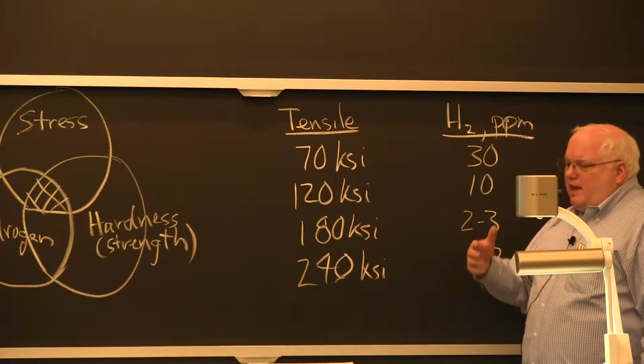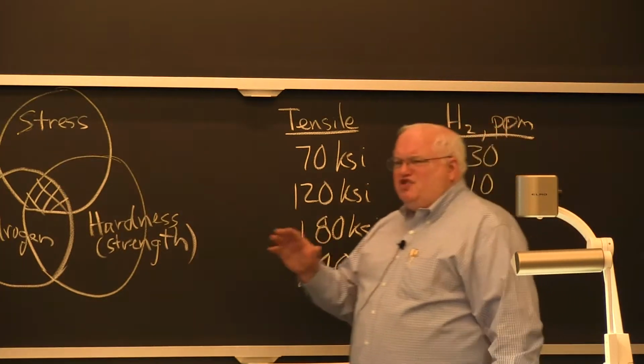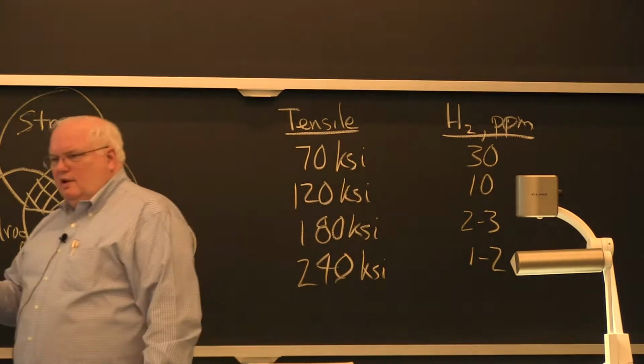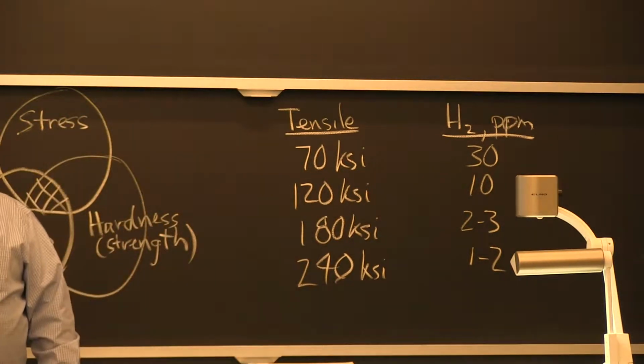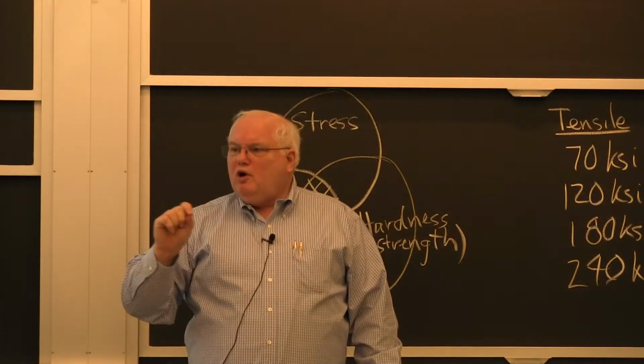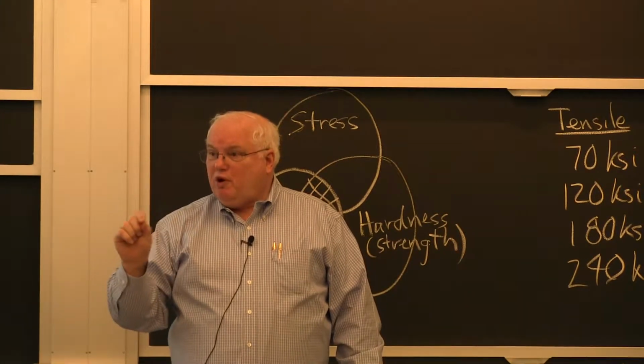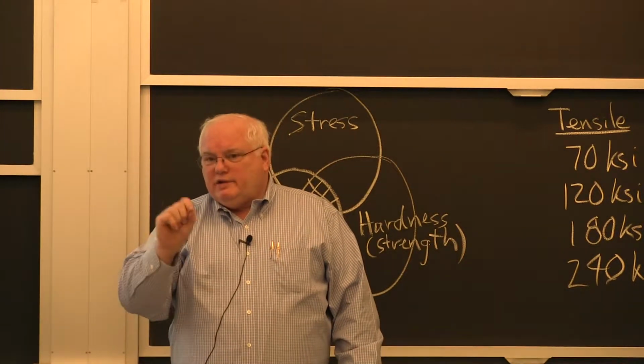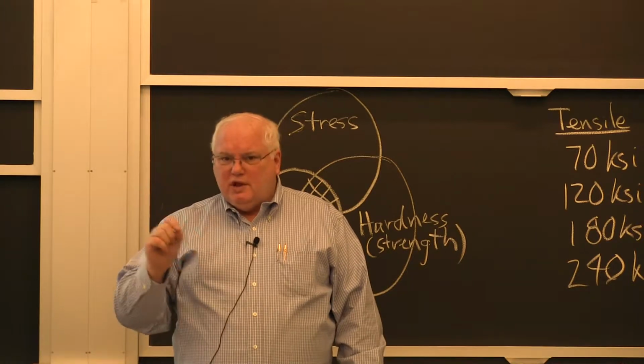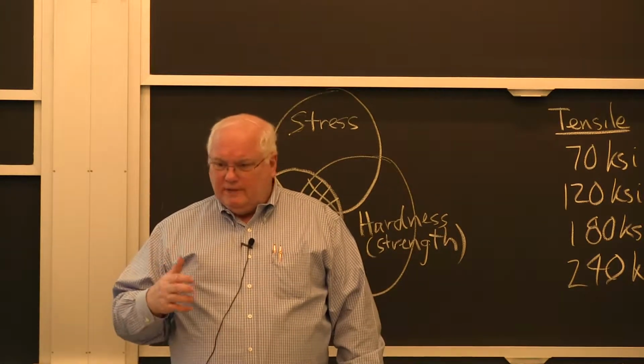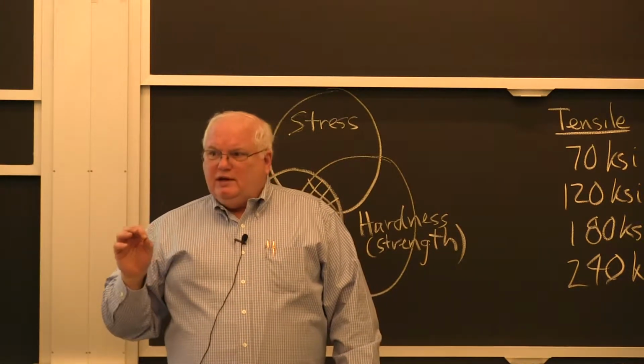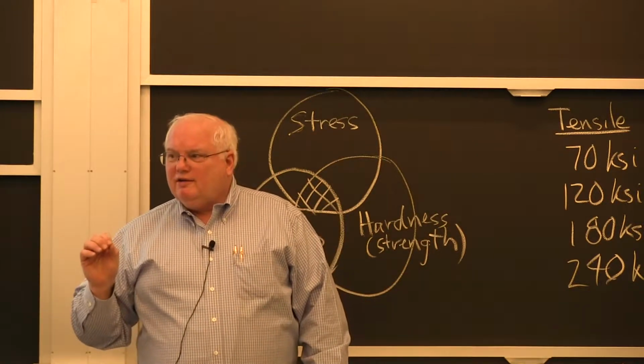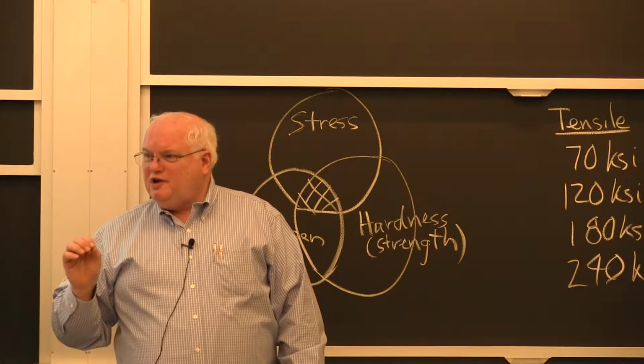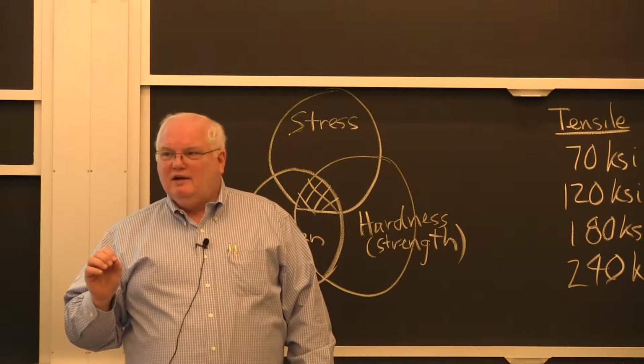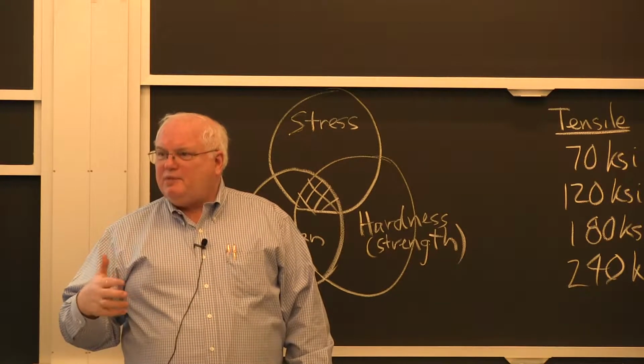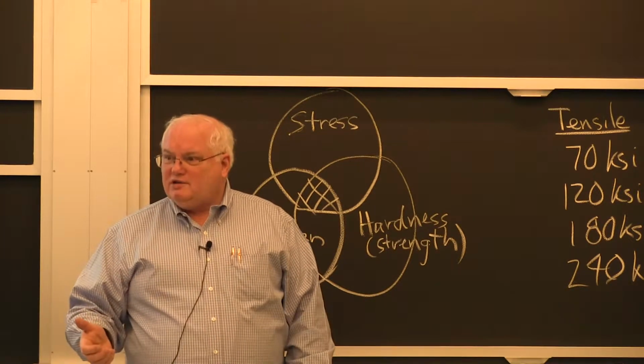Okay? Why is that? Well, there are hydrogen traps in the steel. The hydrogen, not only will it go to crack tips, it will go to inclusions, little dirt particles in the steel. And in fact, there's a guy out at Colorado School of Mines who was elected to the National Academy because he showed that if you have slightly dirty steel, it's better than if you have very clean steel in terms of hydrogen embrittlement. Okay? You want to have some inclusions to trap the hydrogen so it doesn't go all to the bad places.